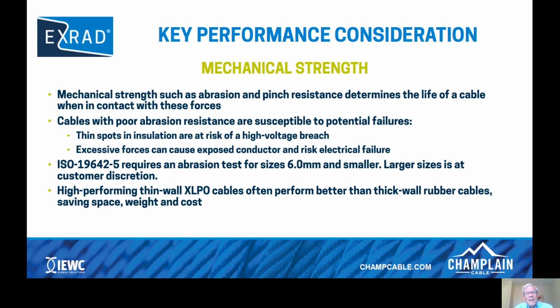Mechanical strength, such as abrasion and pinch resistance, determines the life of a cable when in contact with these forces. Cables with poor abrasion resistance are susceptible to potential failures. In this case, I'm thinking about vibration, where you have conductor to conductor or cable to cable rubbing. Thin spots in the insulation are at risk of a high voltage breach. Excessive forces can cause exposed conductor and risk electrical failure.